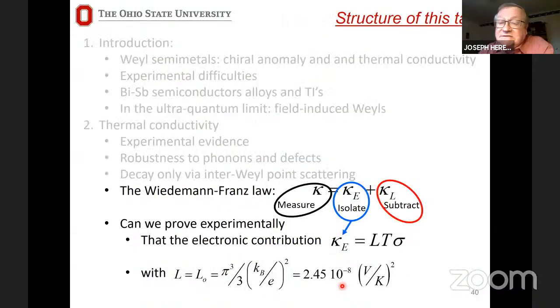So let me show you an experimental verification of the Wiedemann-Franz law, which is really a headache for two reasons. One is, the Wiedemann-Franz law relates the electronic thermal conductivity to the electrical conductivity. But we have to now isolate this kappa_E very carefully from kappa_L. So there is a great opportunity to make small mistakes in this subtraction. Kappa minus kappa_L should give us kappa_E. So that is the first problem. The second problem is all the difficulties in measuring the electrical, the chiral anomaly, the real chiral anomaly, the negative magnetoresistance.